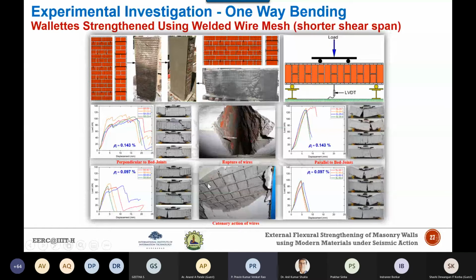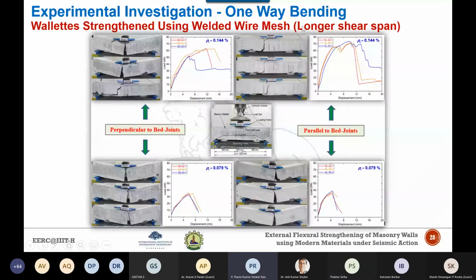Now, in order to understand these failure modes better, we tested a few more specimens using a larger shear span. And now you can see that with an increased shear span, with the same reinforcement ratio, the failure mode has changed from shear to flexure or flexural shear.